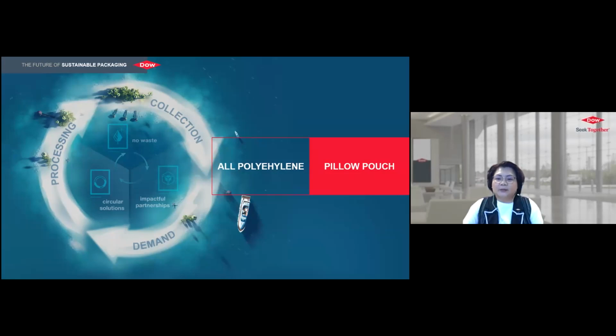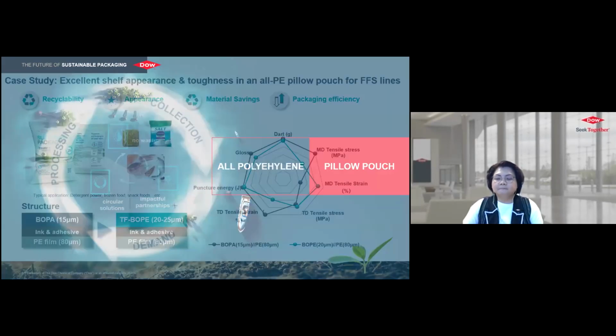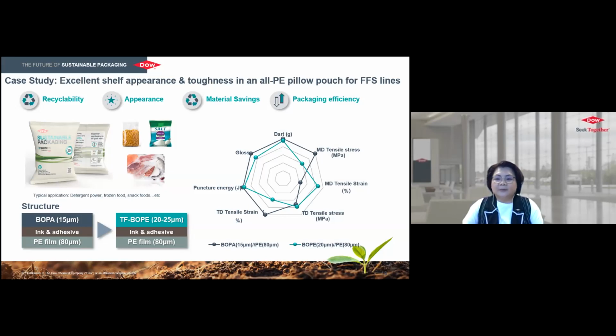So the next packaging format we are going to look at is the all PE pillow pouch. A typical pillow pouch uses BOPP, BOPA or PET as print substrate and laminated to a PE lamination film. Here we use TF BOPE to replace BOPA and laminated to an 80 microns PE lamination film for vertical form and seal pouches to enable the concept of recyclable pillow pouches. The right chart shows the TF BOPE laminates can deliver similar toughness, shelf appearance, and packaging efficiency. The only performance vector lower than BOPA-based laminates is the ultimate tensile stress in the machine direction.